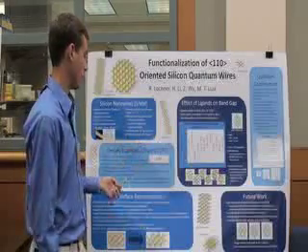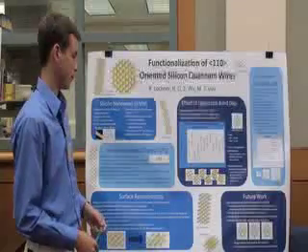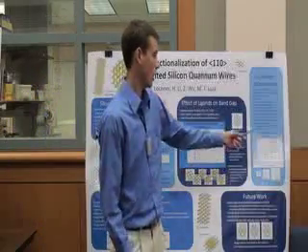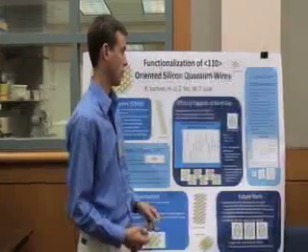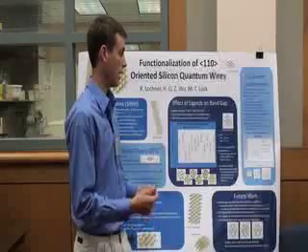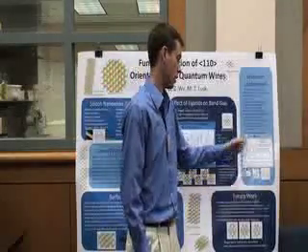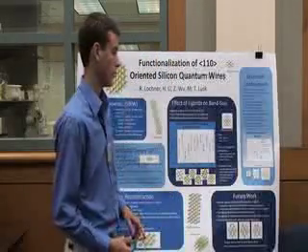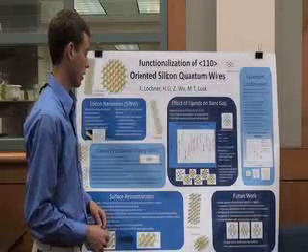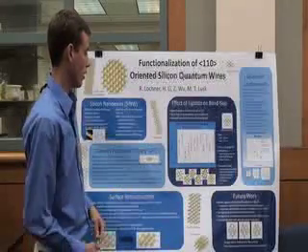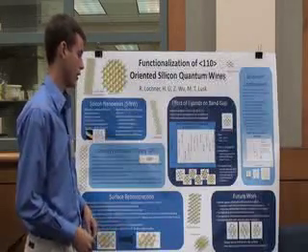An example of the qualitative usefulness of DFT is the fact that although the band gap of bulk silicon is about 0.7 eV in DFT, the actual value is about 1.1. So although we don't know from DFT the exact values of the band gap, we do know that it increases as diameter decreases. So that is a pretty quick summary of what I've been studying this summer.